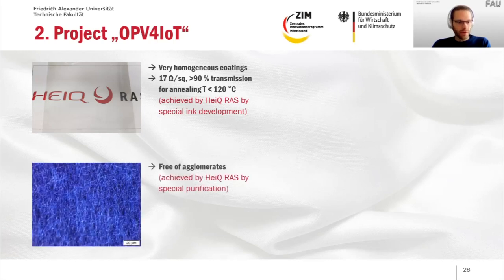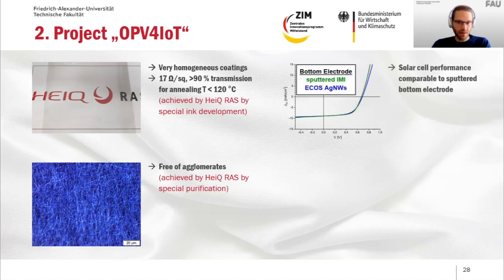And the second very good achievement in this project was achieved by HeiQ RAS by special purification of the ink so that we don't have any agglomerates in that layer, which is the prerequisite for using it as a bottom electrode. And that's what we did then. So we replaced a sputtered bottom electrode with the ECOS nanowires in our solar cells, and the performance was comparable.